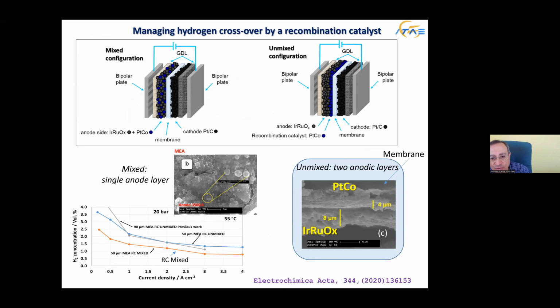How have we tried to solve this issue in our PEM technology? We have introduced the concept of the recombination catalyst. The recombination catalyst is a platinum-based catalyst that can be mixed with iridium oxide at the anode, or you can have a dual layer. So when hydrogen permeates through the membrane, the first layer it encounters and passes is the platinum-based layer. Here, hydrogen can recombine with the evolved oxygen, or be electrochemically oxidized.